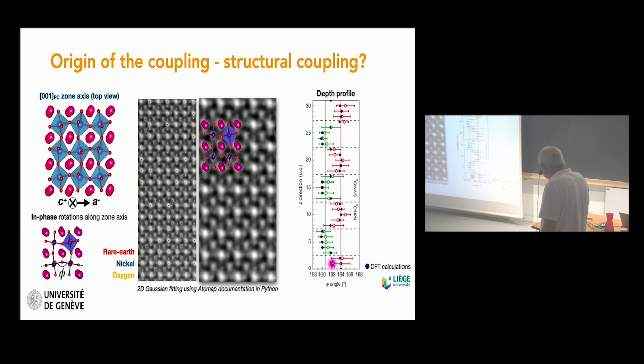When you go from one material to the other, this is now the nickel-oxygen-nickel bond angle as a function of the depth in the superlattice. You see that very rapidly you go from one value to the other, and both the measurements and DFT calculations are telling us the same thing. So it's not a coupling of the distortion. So what is the reason for this coupling?